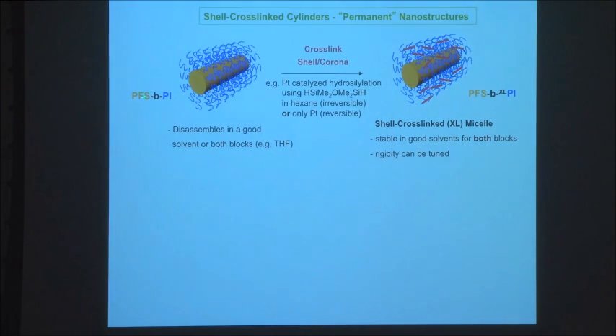So if you take, for example, PFS polyisoprene cylinders, which you can make in hexanes, and add a good solvent for both blocks, such as THF, it will disassemble. But the polyisoprene chains have vinyl groups present, and you can actually join these together using platinum-catalyzed hydrosilylation by adding a silane material. This will introduce covalent crosslinks, which I've indicated in red here, into the corona. And this fixes the structure in. This can no longer disassemble.